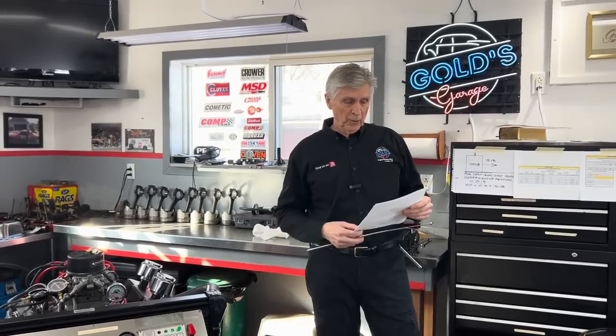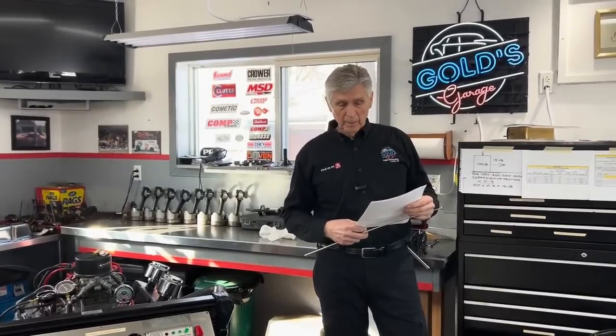5/64th. So 5/64th is .078, by the way. .078. You use a .043 moly plasma ductile iron top ring. Okay, and then the second ring was also moly plasma 1/16 second ring, and then 3/16 light tension expander rings.